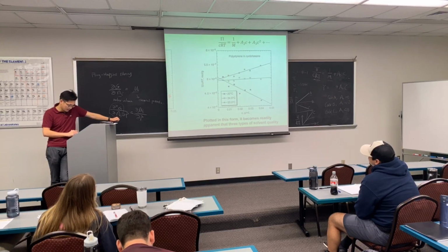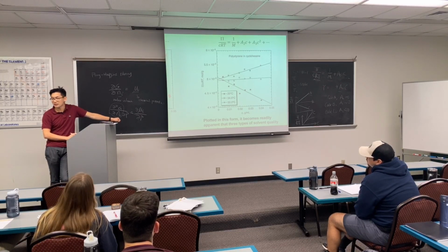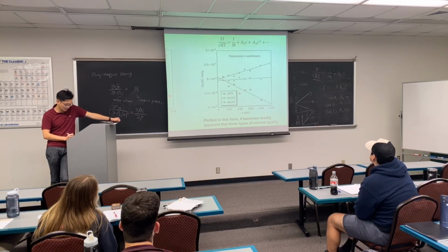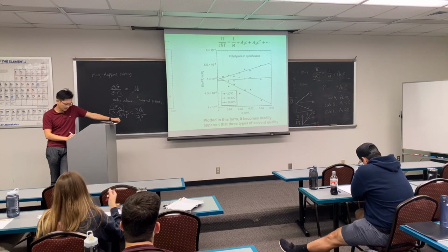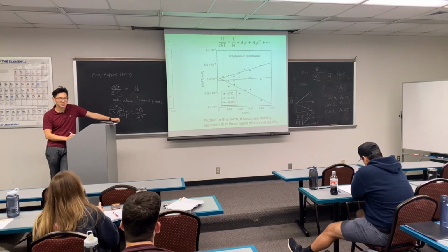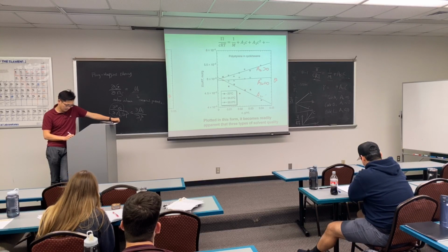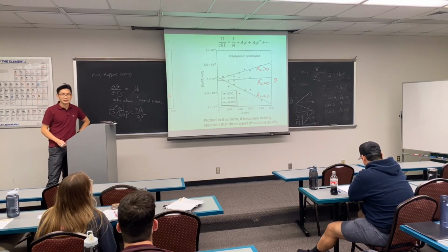And if we take the same data and plot this way, that's what we talked about. Not plotting osmotic pressure directly, but dividing by concentration. This is what you would have. And this almost horizontal line suggests A2 is equal to 0, or theta solvent. This A2 is larger than 0. This is A2 smaller than 0. Experimental data. Okay?